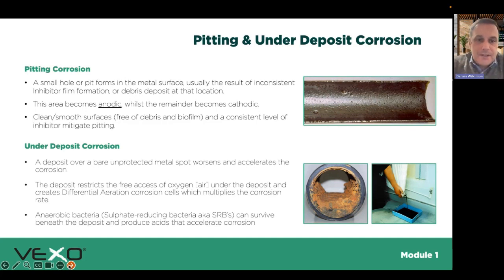At the same time, we have under deposit corrosion. As you can see in the bottom left picture, deposits settle out in a low flow area, or as the flow rates encourage things to settle out, like you see there on the radiator. Below the deposits, we have a lot less free oxygen available, and above the deposits there's a higher level of oxygen, and so that creates an electrochemical reaction that drives corrosion locally underneath, hence under deposit corrosion.